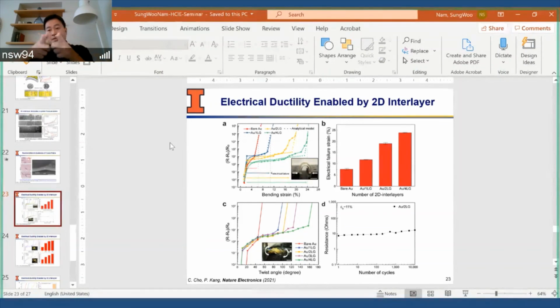You have two bridges and you can do this in-plane, but you cannot do this, so this is gone. And that also brings back the gauge factor. If you completely restrict the out-of-plane motion, the gauge factor comes in. So stretchability-wise, out-of-plane is very important. There's a limited operation regime if you restrict that, mechanically but electrically as well.